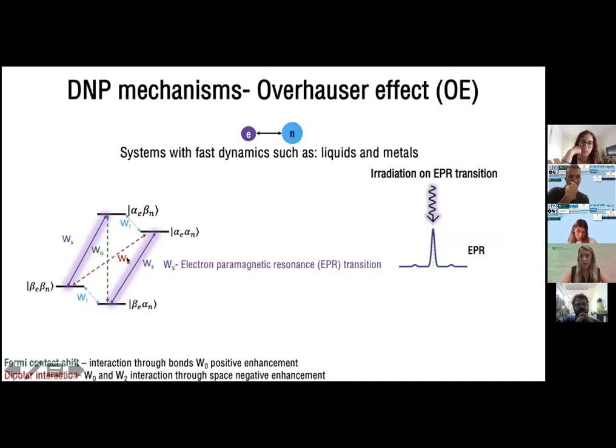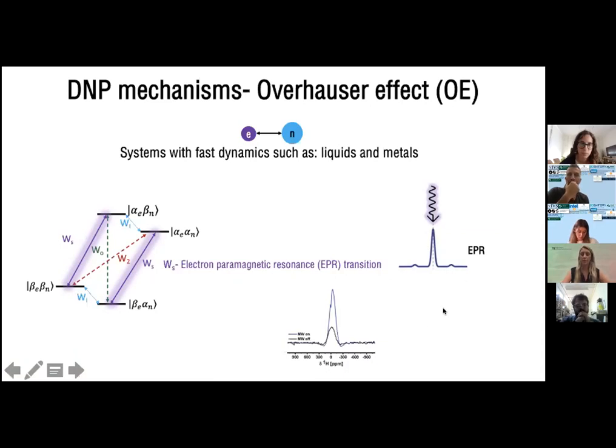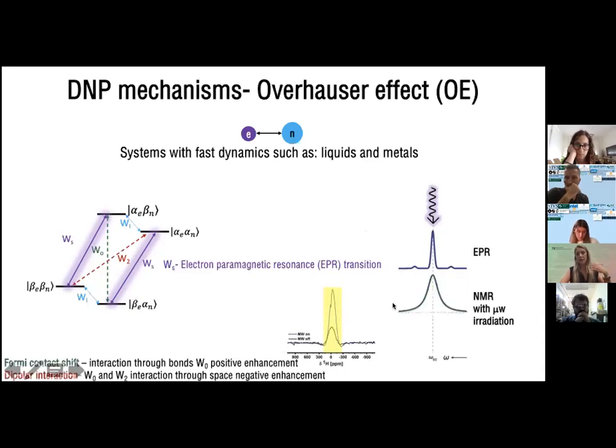You can see here transitions that can give you NMR enhancement, the DNP enhancement is here. And how you practically verify if you have this Overhauser DNP in your system. So you irradiate different points in your spectrum of the EPR, as you can see here, and then you record NMR in each of these points. You integrate them and you plot the intensity, as you can see here.